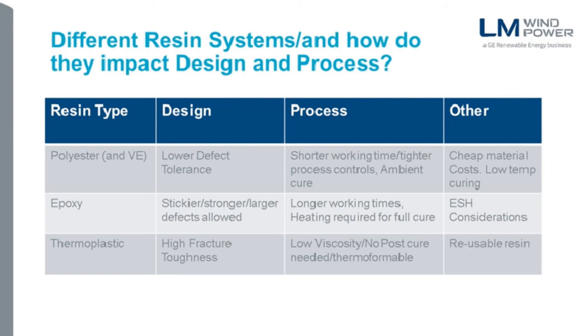The downside, from a design perspective, this was a designer that I was talking to, is that you have low defect tolerance. The structure can't put up with large defects without needing repair, which from a process perspective is not good, because if we have defects, they need to be repaired, and that takes rework and extra time.